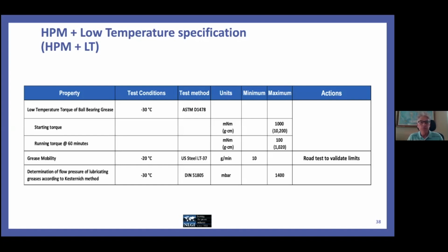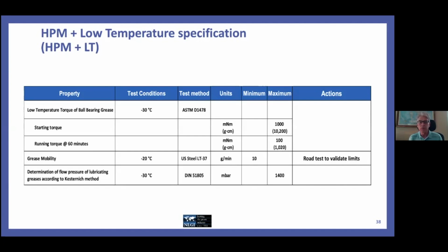And then the final test is a DIN test method, the DIN being the Standards Association out of Germany. This is another sort of a version of the mobility test, but it is different. And we've come up with -30C as the appropriate temperature. And this test you run until you see what the maximum pressure is required to move the grease at -30C. And we've set that at 1400, which is also in line with the DIN low temperature limits in their specifications.